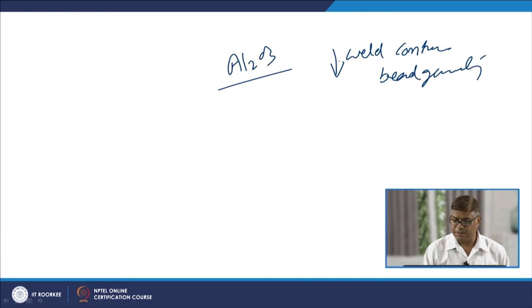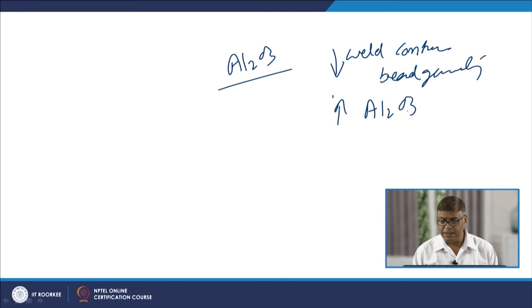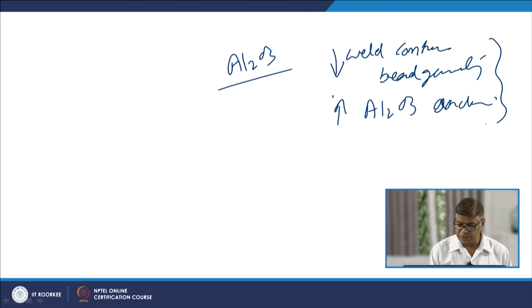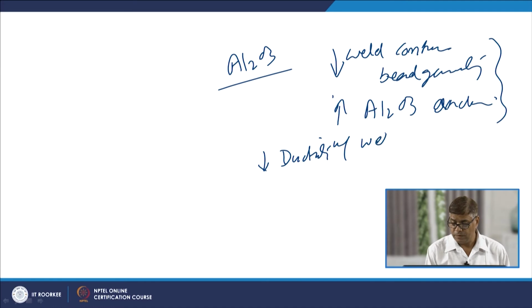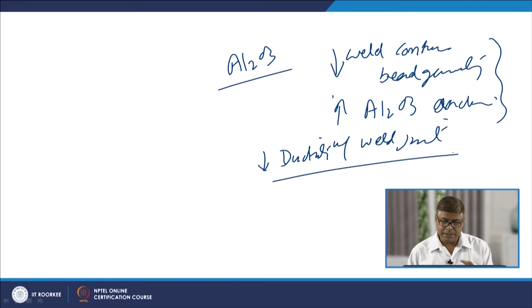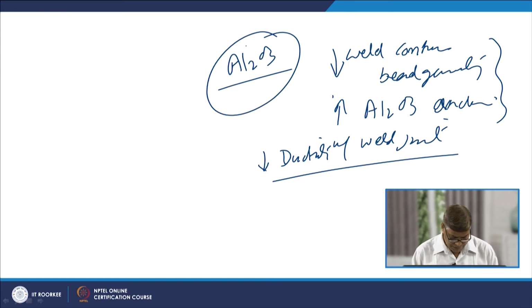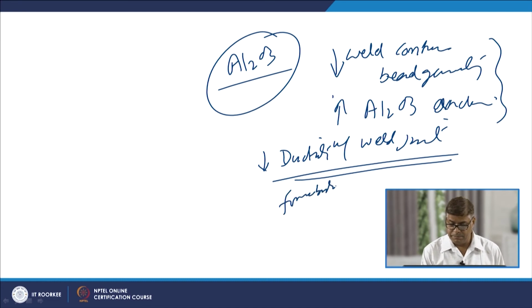is badly compromised. At the same time, the presence of Al2O3 in the weld metal acts as an inclusion. So, weld bead geometry is poor, and when it is present in the form of inclusions, these lower the ductility of the weld joint. So, basically the formation of Al2O3 is a major problem as far as the SMAW of the aluminized steel is concerned, which in turn lowers the ductility and the formability of the joint.